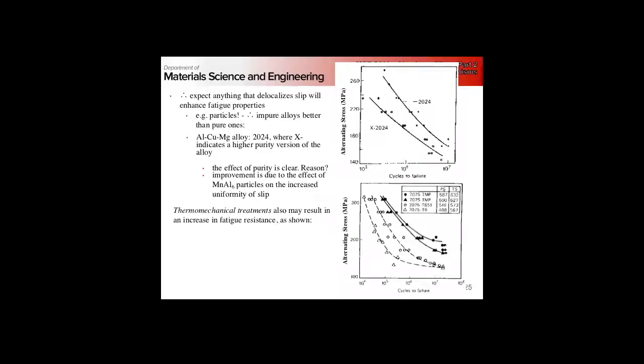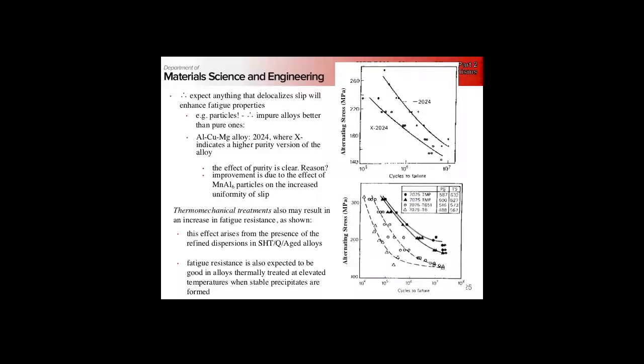So we can also go through thermomechanical treatments to increase our fatigue resistance, right? If we can get a really good fine dispersion in our solution heat treated, quenched, and aged alloys. Remember the path that the dislocation took through our GP zones? Really fine particles.